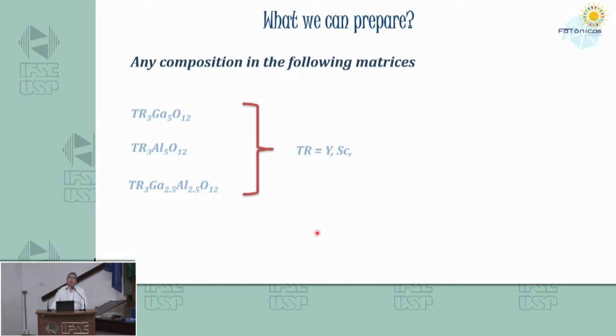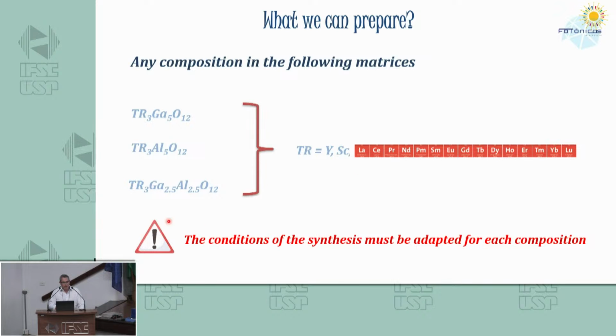Okay, so we have gallium garnets, but one of the most known is aluminum garnet. And if you replace gallium by aluminum, what's going to happen? It works too. We can have aluminum garnets with the rare earths. And this is the nice thing about this system. You put it all together, it's almost like cooking. You put everything into the furnace, you just control the speed of the quenching, and then the crystals will be formed. Okay? And the amount of rare earths you put into the composition, we will find inside the crystal.